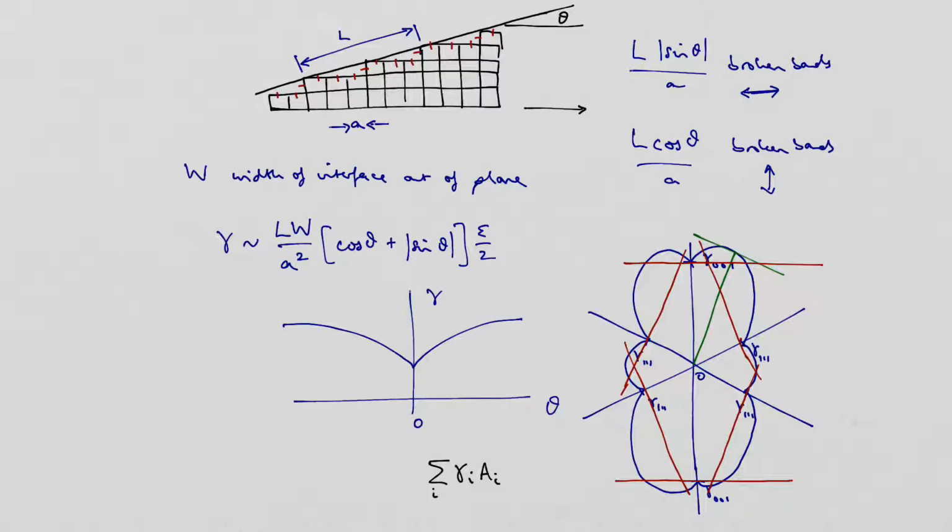That's not really within the remit of this course, but as we're passing by, you probably ought to be aware that thermodynamics is nothing to do with kinetics. Kinetics is all to do with the rates at which things can happen, but thermodynamically, the lowest possible energy for a finite crystal is the one that will have this sort of combination of surfaces. And sometimes you can see that. Sometimes you can do this Wulff construction, look at the equilibrium shape you'd expect to get out, and then spot that it's the same as what you see.